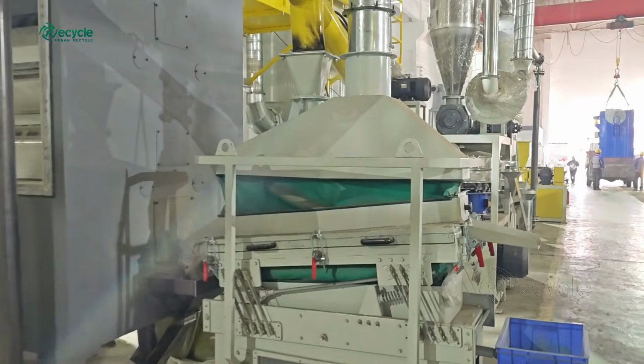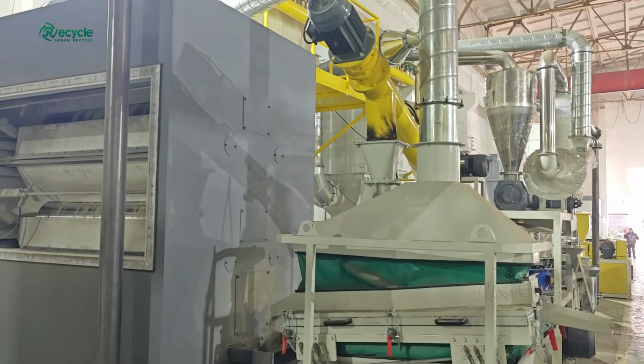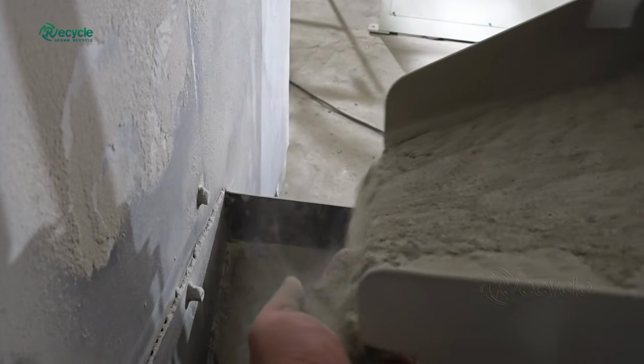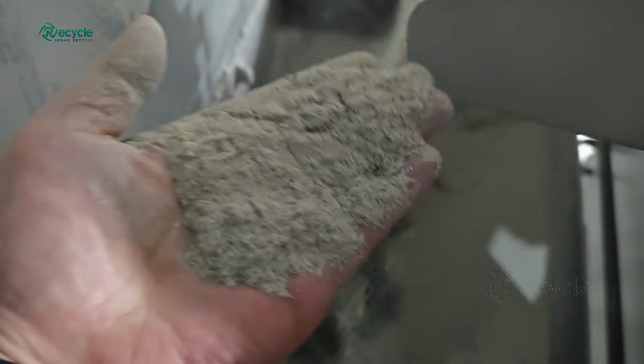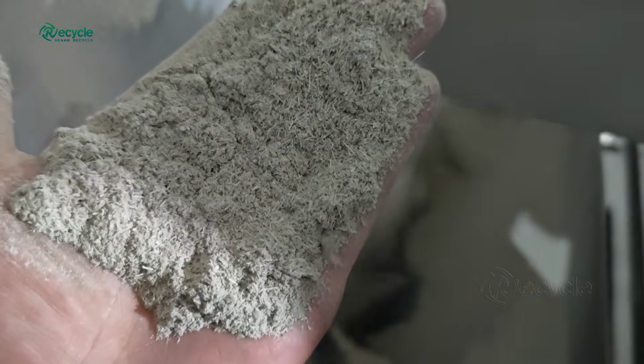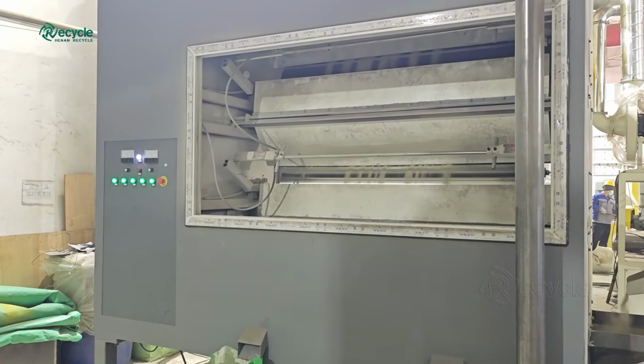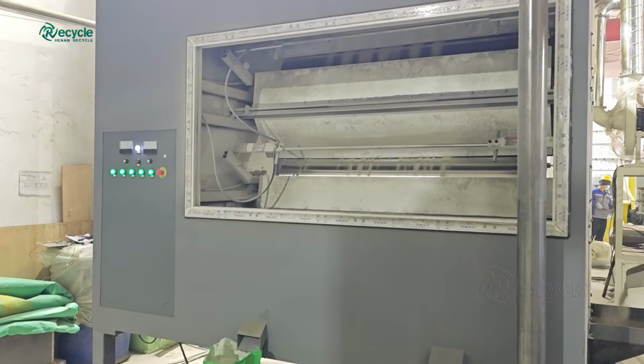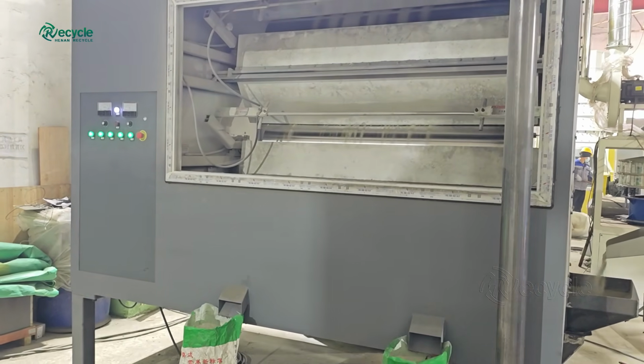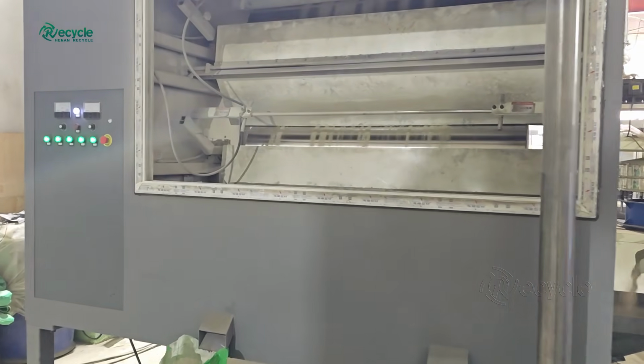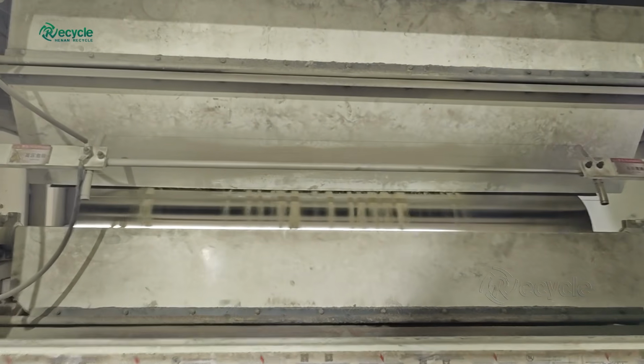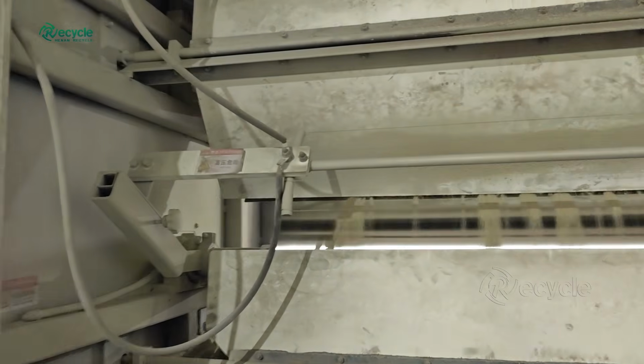Based on density differences, heavy metal particles such as copper and solder are separated from lighter resin and fiberglass powders. This stage is the core of copper recovery, where the majority of metal is efficiently concentrated. To further improve recovery efficiency and product purity, the remaining material undergoes electrostatic separation. This final separation stage removes residual metal particles from the non-metal fraction, minimizing metal loss and significantly reducing copper content in the resin and fiberglass output.